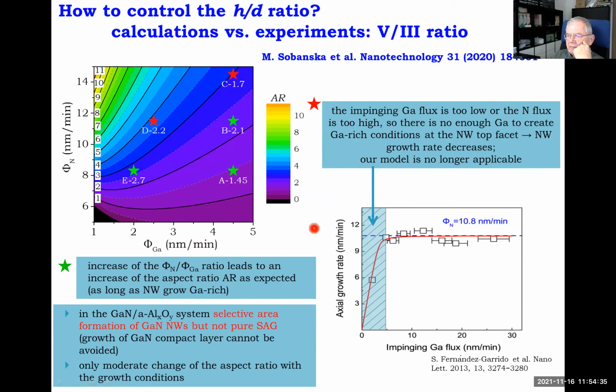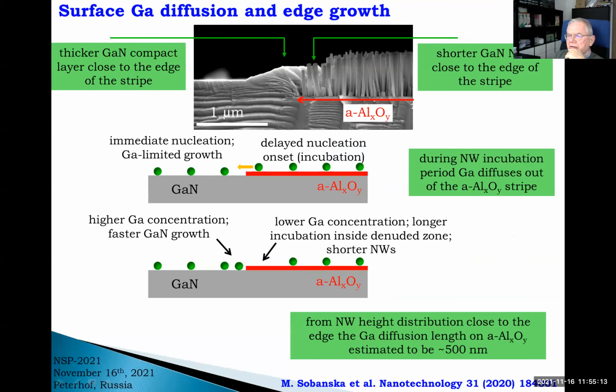What's wrong? Well, our assumption is wrong. These structures indeed grow under locally gallium-rich conditions, which appear at the top surface of the nanowire due to the diffusion of gallium atoms along the side walls to the top surface. However, if we put too much nitrogen or too low gallium fluxes, then this condition that we put into the model does not work.